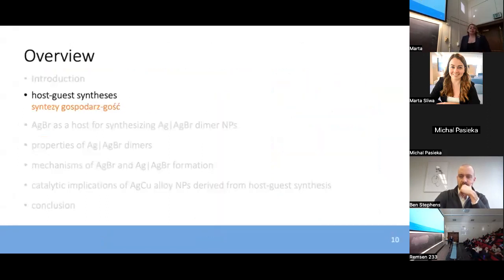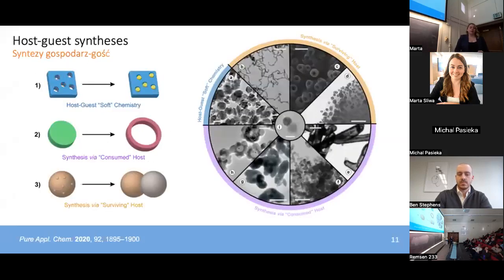So at this stage, I'd like to introduce a slightly different technique that we haven't yet talked about that can also be used to make multi-component nanoparticles, called host-guest synthesis. Host-guest synthesis can be broken down into three broad categories. In the first, nucleants or reagents for a particular process are harbored in the pores at nanoscale volumes of a host, and in those pores, they interact to form that secondary material. In the second category, the host is consumed during the formation, and all we have left at the end is that secondary material that the host was used to make or create. And in that third category, the host survives the process, a secondary component is extracted out of the host in some way, and that host remains as part of that multi-component nanoparticle at the end.